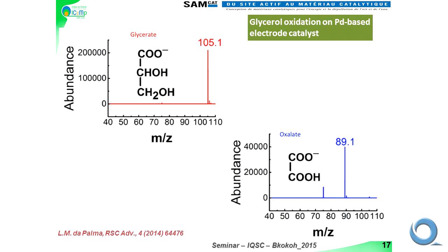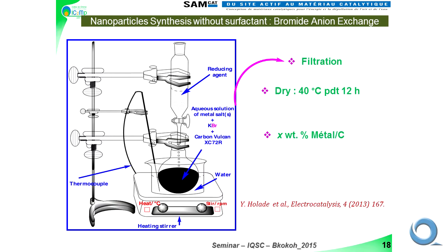This means that we prepare, as I told you, by bromide exchange with chloride. We have a student, Yaovi. He said, I can improve this system. So this is his apparatus, a reflux system. It's very simple. And he used an excess of potassium bromide. And at this time, he exchanged the chloride of a metal precursor with a complex. So when he has this exchange, he heats at low temperature.